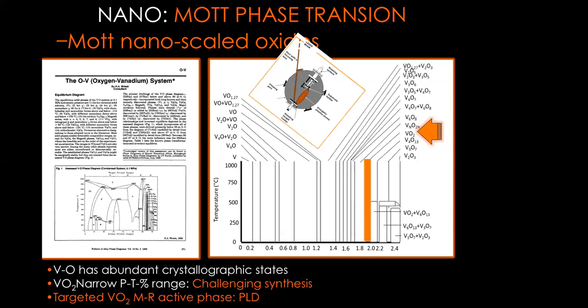The ideal is to have a vanadium oxide transiting at 25 degrees Celsius, while the one which is close to 25 degrees Celsius is VO2. There are others which transit at 120 or minus 50, something like that. But the one which transits close to room temperature is VO2. Okay, thank you very much, sir. Really appreciate it. Thanks.